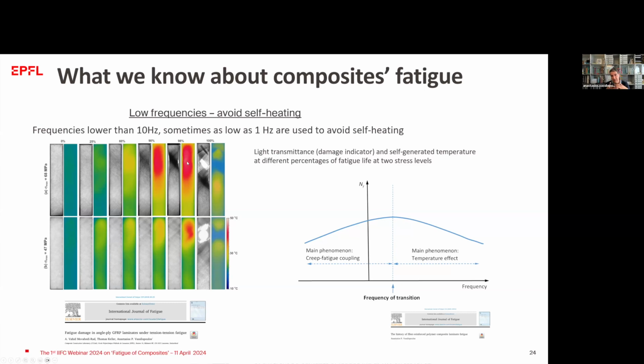And this is because of the internal friction that comes when you have damage, you have cracks, and the material starts creating temperature, heat, because of the friction internally in the structure. So what we know today is that there is an effect of this frequency on the material behavior. When we exceed a critical frequency, if you like to call it that, we have temperature increases and the life decreases because we actually soften the material.